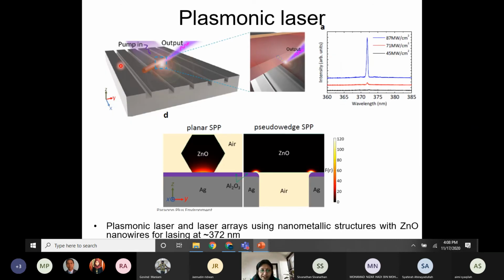Plasmonic laser and laser arrays using nanometallic structures with zinc oxide nanowires for lasing at 372. So this is lasing at 372 over here, the blue color, all right, with the input power of 87 megawatt. So this is the zinc oxide nanowire over here, and this is the cross section of it, and you have light emitting out from this nanostructure. So it just shows the schematic of the structure.